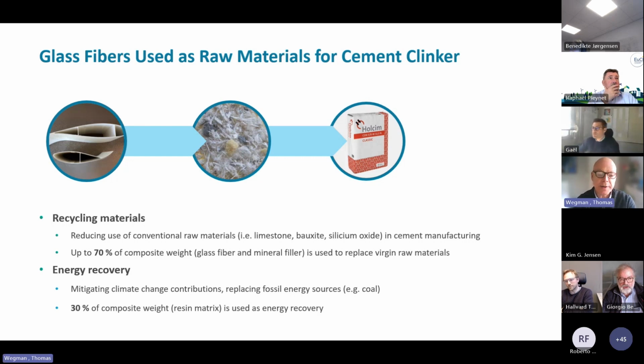30% of the composite waste, the matrix, is burned, and that is replacing fossil energy sources, for instance, coal. But there are also different sources like lignite, brown coal, and petcoke, which is a heavy oil fraction. And we all see that by doing that, it is possible to save CO2 in a nice way. Again, it's not reinforcement of concrete; it's really melting the material and using it as a raw material for making the cement.